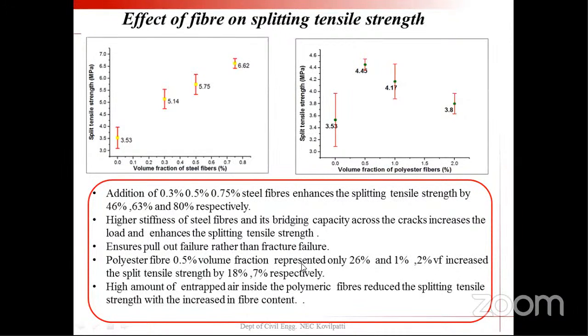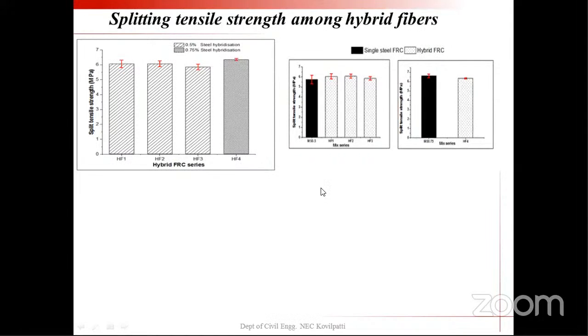But when you look at the polyester fiber, the improvement is 18% and 7%, because once the polyester fiber was added, we observed a lot of entrapment of air inside the concrete, which totally reduces the strength of the concrete. And this comparison is also made.